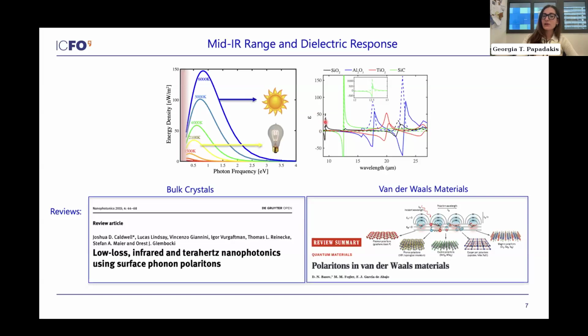So in the mid-IR, if I look at the dielectric function, so this epsilon here is not emissivity, it's actually the dielectric permittivity, you'll see that dielectric materials have these very narrow phonon resonances. When the dielectric function goes negative, this is what we call the Reststrahlen band. And it's a very interesting regime because when the permittivity is negative, we have these surface polaritons that propagate in the material. And these phonon polaritons, in contrast to plasmon polaritons, have a very narrow bandwidth, which makes them very low loss. Now, there are many important papers about this topic. Here, I just put 2 review papers, one for bulk materials, conventional dielectrics, and one for van der Waals materials.